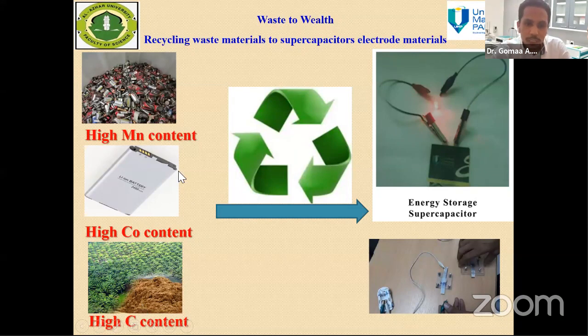For example, from spent zinc carbon batteries, we can recycle manganese oxide to be used as a supercapacitor material, and from lithium ion batteries, which have a high content of cobalt, we can recycle cobalt oxide and use it as a supercapacitor electrode material. And from different agriculture waste, we can recycle carbon in different forms, porous carbon nanostructures and carbon nanospheres, and use them for supercapacitor applications.